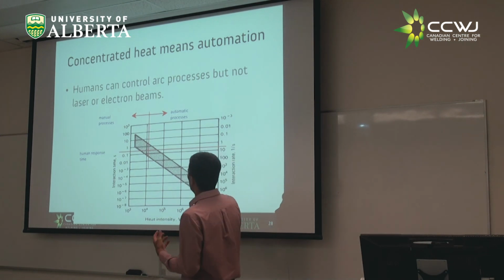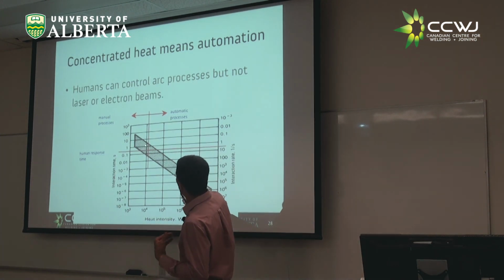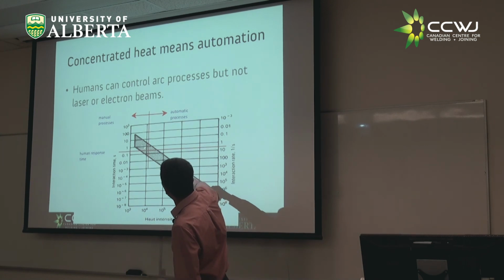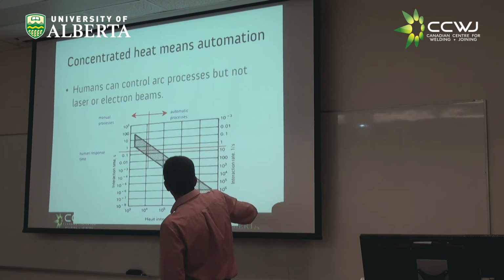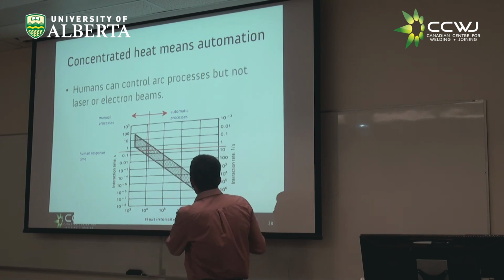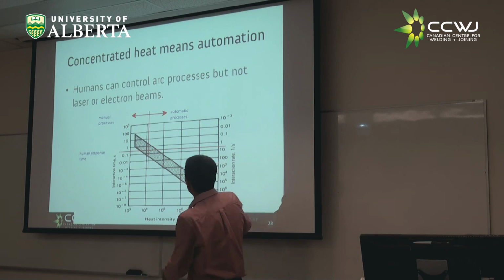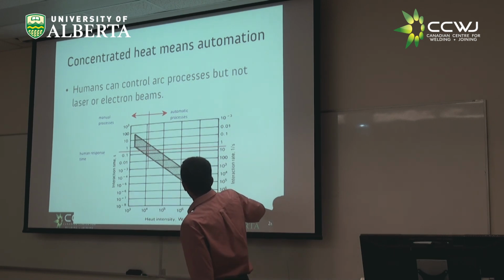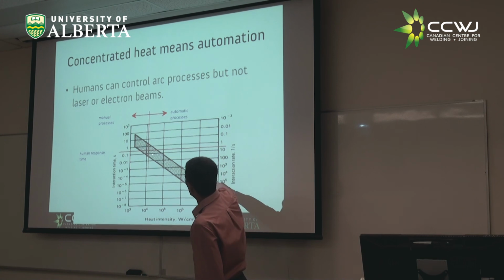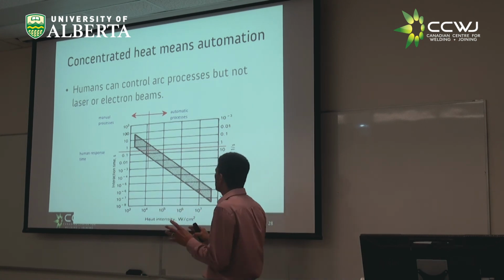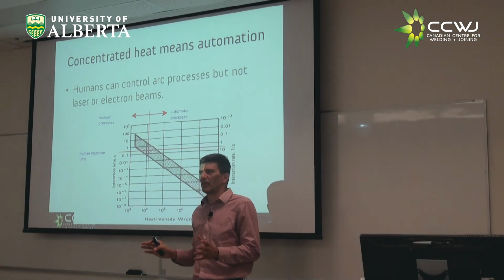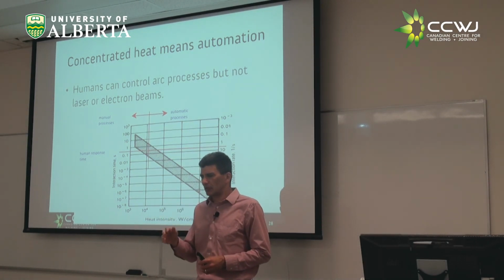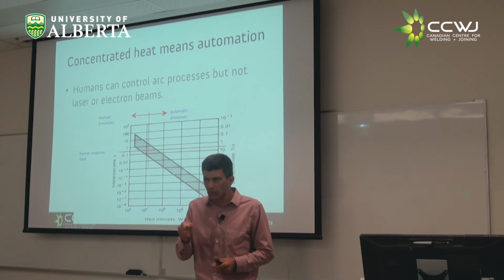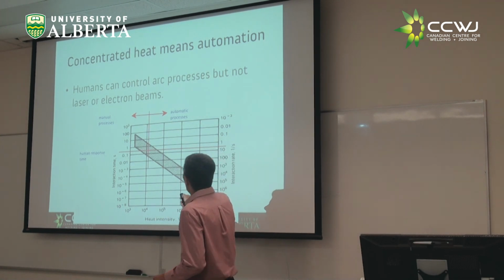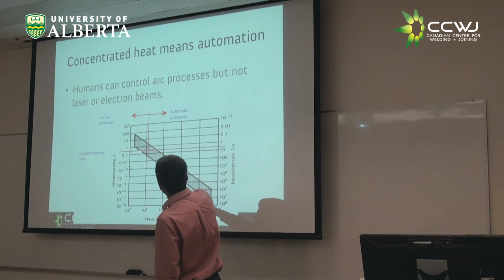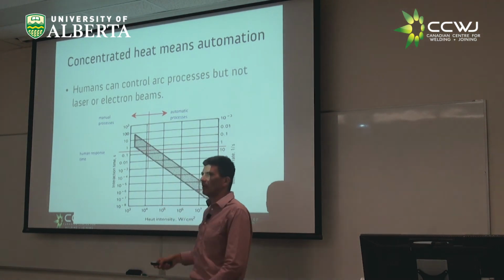And you can calculate this interaction time, right? And this is the range. This is a calculation of my advisor, Tom Eagar, at MIT. He says, depending on the intensity of the process, and here we have laser beam, then arc, and then flame, the interaction time gets shorter and shorter as the beam is more and more concentrated. Interaction time of humans is of the order of 0.3 seconds. This is the time it would take you to step on the brake of your car or to correct your torch as you're welding. And you see where the interaction time humans have compares with the interaction time of the weld.